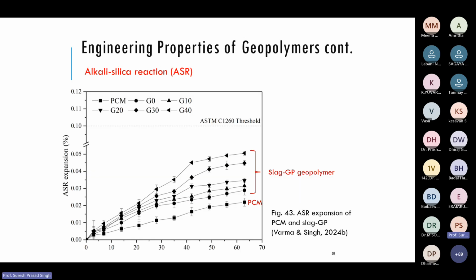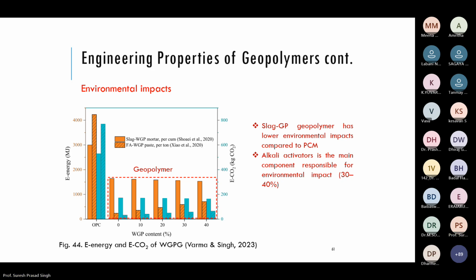Similar to alkali silica reaction, here also the geopolymer concrete and all these things are all below the limits. Here these are within the limits specified in ASTM C1260, but here it is a slightly higher alkali silica reaction expansion compared to Portland cement. This is just the opposite behavior we have seen here, but it is much within the limit. It is less than 0.05, but the limit as per ASTM is 0.1 for alkali silica reaction, ASR. Like this, we have seen this. Then the energy and carbon dioxide release.